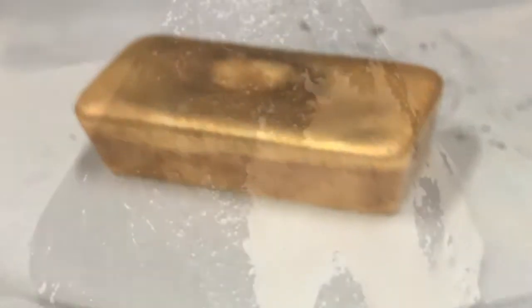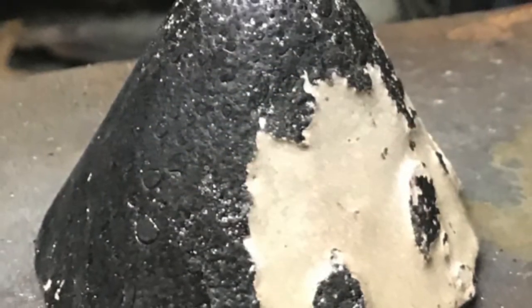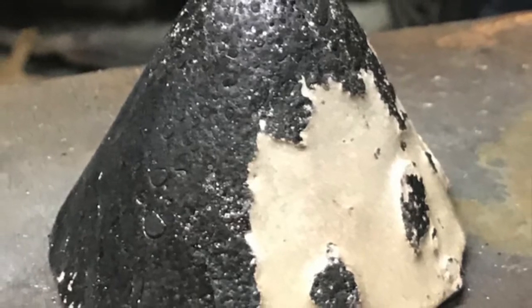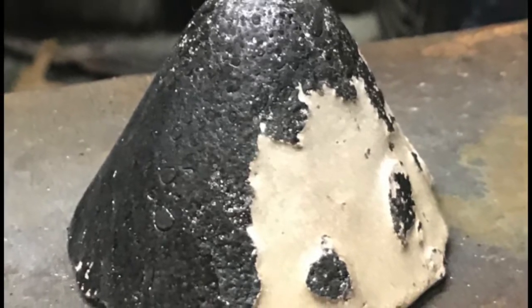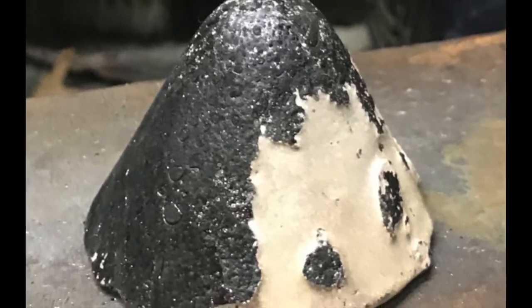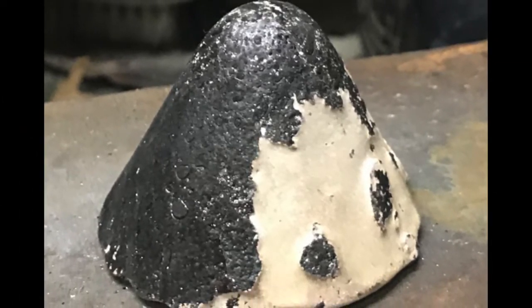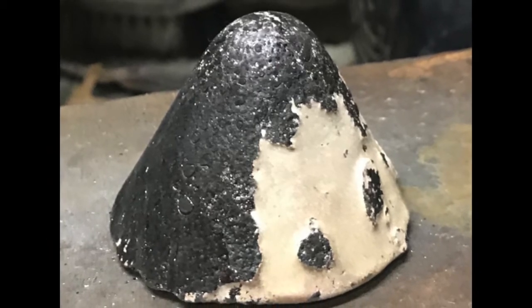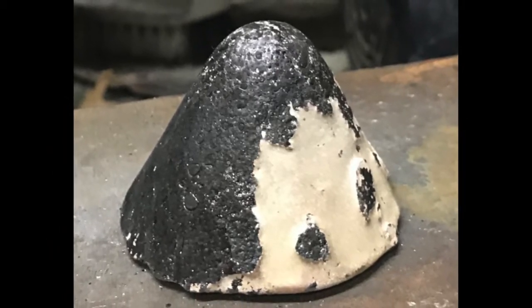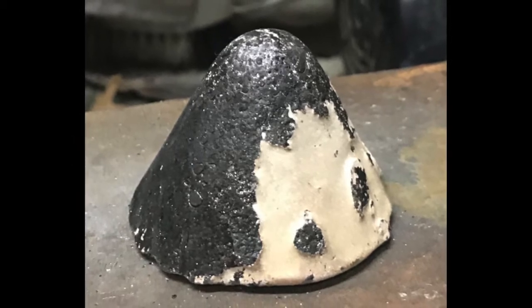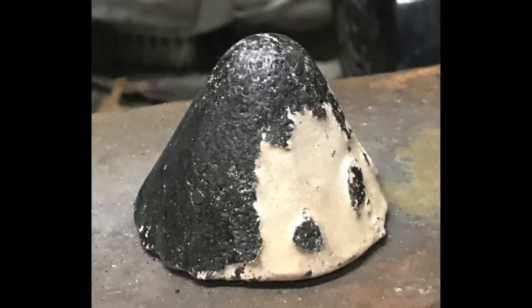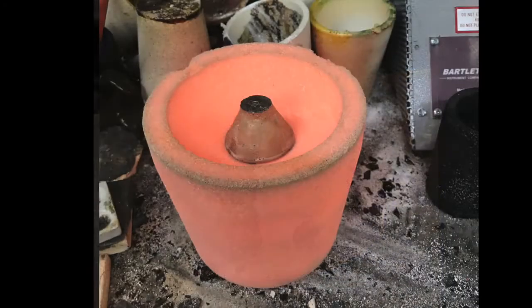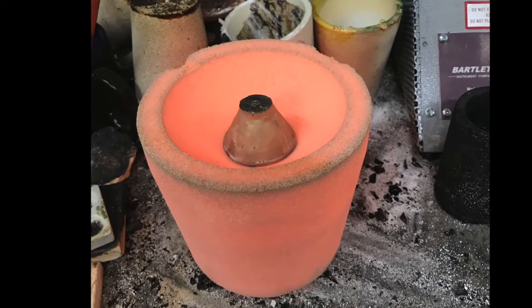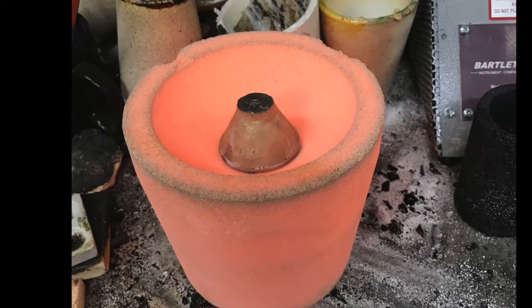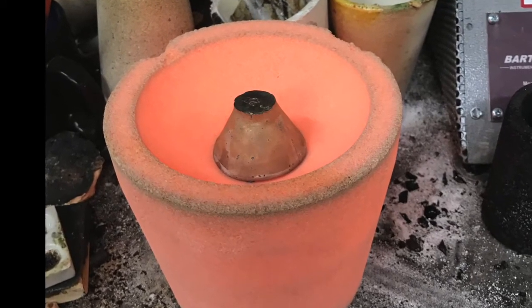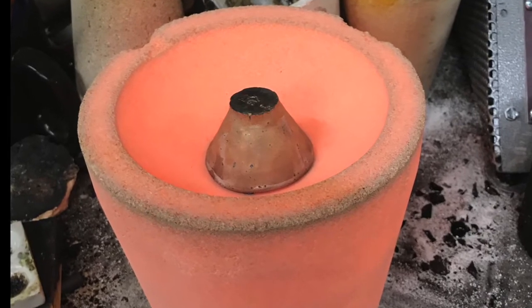Now, that was from the coarse material. Some of the material was a higher grade with much higher precious metal content. This prill right here shows that it's a much higher precious metal content, as you can see from that light color. The dark color is just leftover slag that hasn't come off of it yet. Here it is being put in the hot cupel before getting put back into the oven. The top's been beat down a little bit, which knocked away that excess slag.